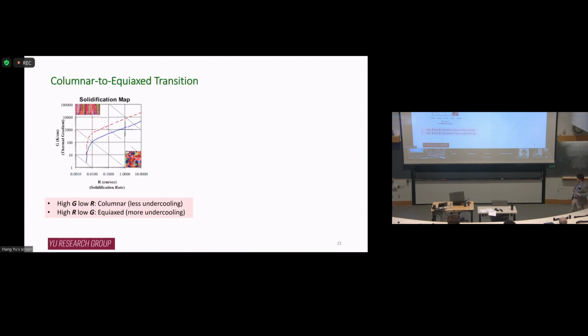Actually, that's not new knowledge. If you look at the welding literature, people already figured it out. There are 2 parameters that are important. One is the thermal gradient G. The other is the solidification rate R. If you can have a relatively high R and low G, you can promote undercooling, so you have a better chance of homogeneous nucleation inside the molten pool. By doing that, you can get equiaxed grains, right, rather than columnar grains.